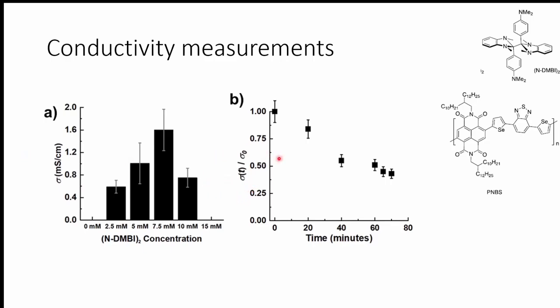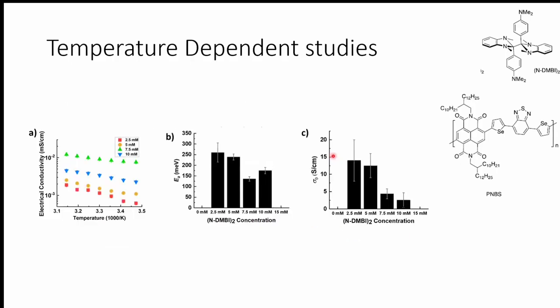Now, the other thing that we wanted to measure is how conductivity is changing in air. We only exposed it to air for the first few minutes of our measurement, and we saw it did not immediately decrease. There was a slow decrease over 75 minutes to half the value. So it displayed sufficient air stability to do all of our experiments in air, which was another good thing about the study: we didn't need extra sophisticated glove boxes, we were just able to do it in air.